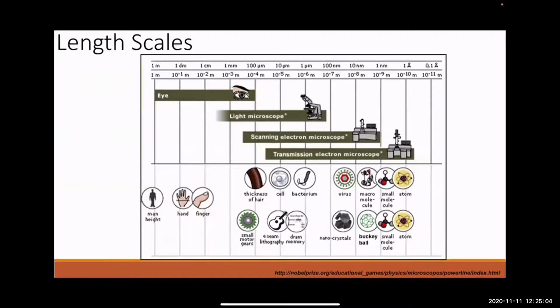So that's summed up nicely in this sort of chart here, which shows the length scales involved and what you can do with your eye. And of course, with your eye, it's going to depend on how close the feature is, and people's eyes are different, but it's typically limited to somewhere around 1/10 of a millimeter or 100 microns, which conveniently is about the size or thickness of a human hair here. LM, light microscopy, as I mentioned, can get us down to about 200 nanometers or so before the diffraction limit sets in. But that's good enough to see things like cells, for example, bacteria, things like that.